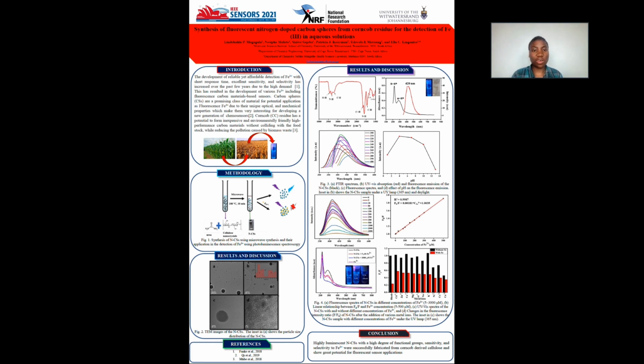Selectivity studies were then conducted to determine if our material can detect iron 3+ in the presence of competing metal ions. As we can see, the red represents the iron 3+ with the other metal ions, and we can see that the intensity of our material with the different metal ions with iron 3+ tends to decrease drastically. This is because our nitrogen-doped carbon spheres are highly selective to iron 3+.